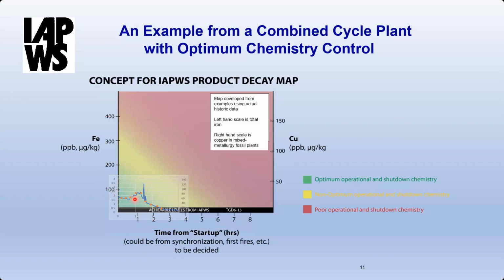Green area indicates that the plant is operating with optimum chemistry control during operation and has reasonably good shutdown conditions. Contrasted by that, if you're in the red area, that's poor operational chemistry and shutdown chemistry. So this trace superimposed on this decay map provides you an indicator of whether the chemistry is okay or not. And this trace here is from a good combined cycle plant in Denmark that we monitored.